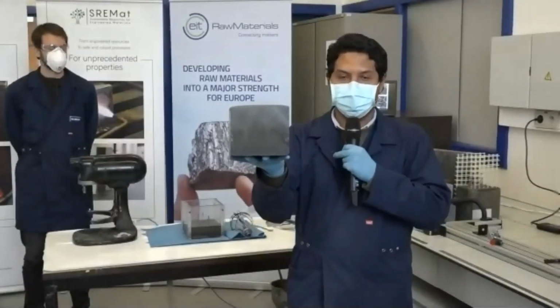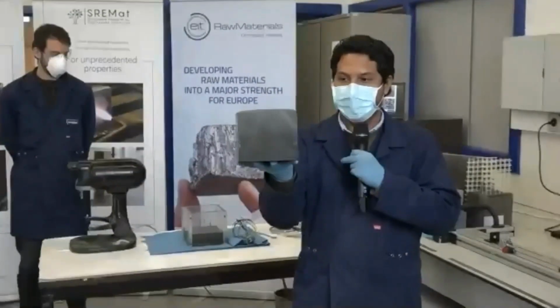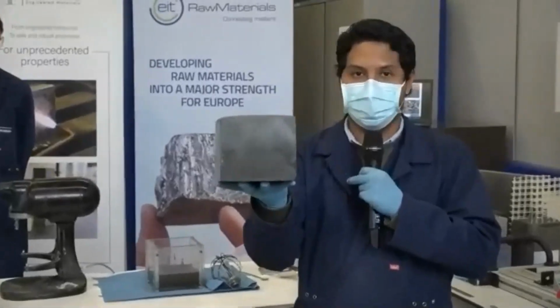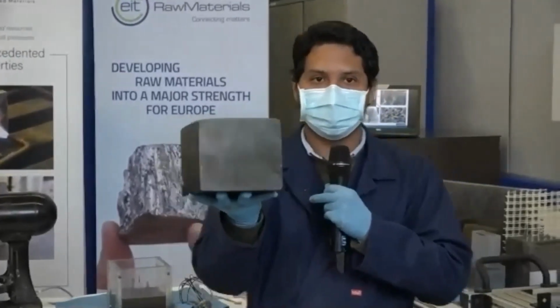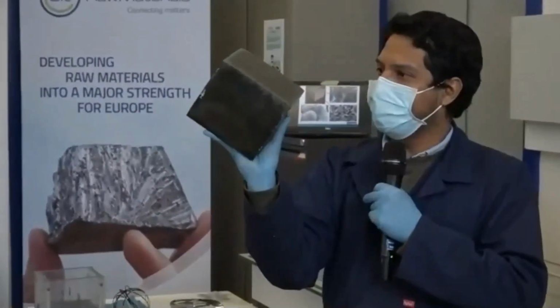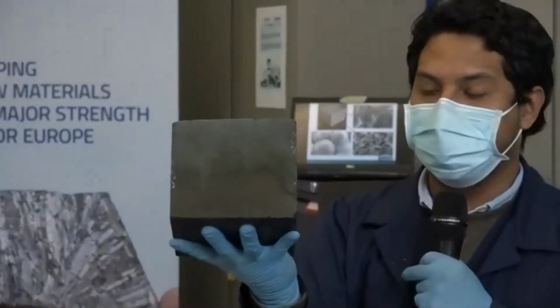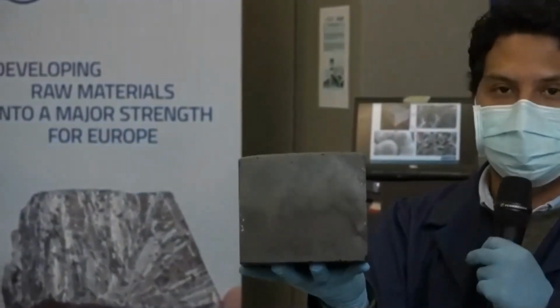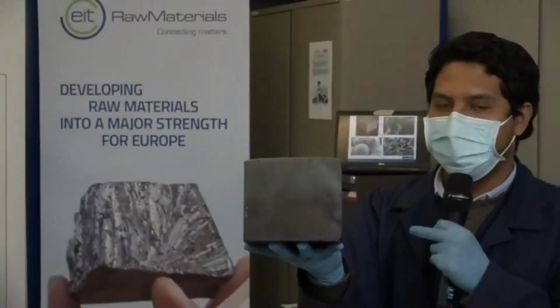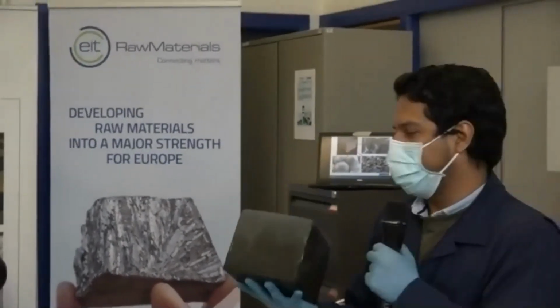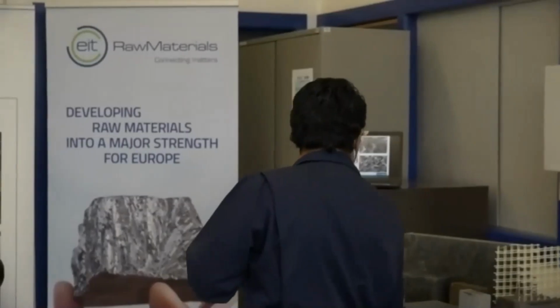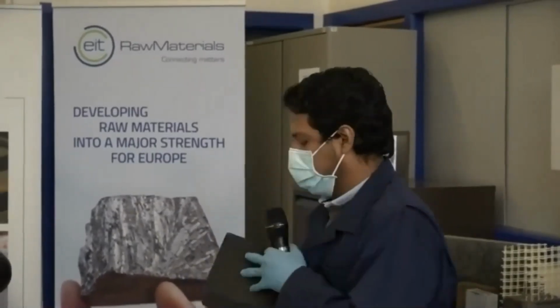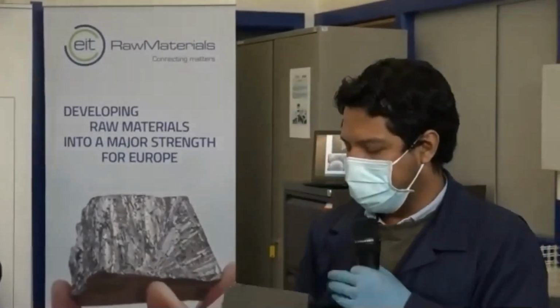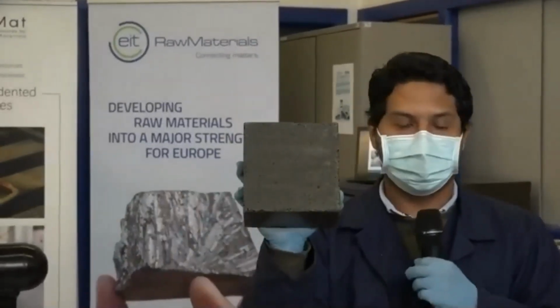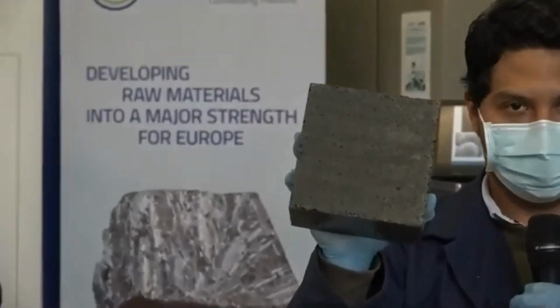As you can see over there on the top, you have a kind of a curved surface. We call it here in the lab a muffin top. Now you cannot see actually the porous structure here, but normally what we do here is that we remove the sides, normally, the muffin top, and I have also a sample prepared for that, so you can actually see it. If you remove that muffin top or the sides of the sample, what you will see is something like this. As you can see over there, then you have a porous structure.